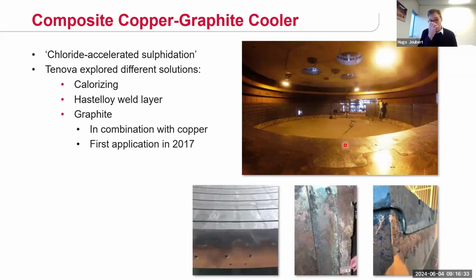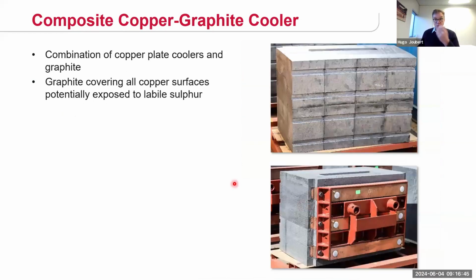One of the issues we did pick up here is that you do still get sulfur coming in between the adjacent coolers, and then it attacks the copper behind the graphite. So what we did for furnace 1 for this upgrade is we developed a composite copper graphite cooler that combines copper plate coolers with graphite. What is unique about this design, the Tenova design, is that the graphite not only covers the hot face of the copper, but it also completely covers the top, the bottom, and the sides of the copper, as you can see in this composite cooler design. So there's no way for the sulfur to get to the copper.